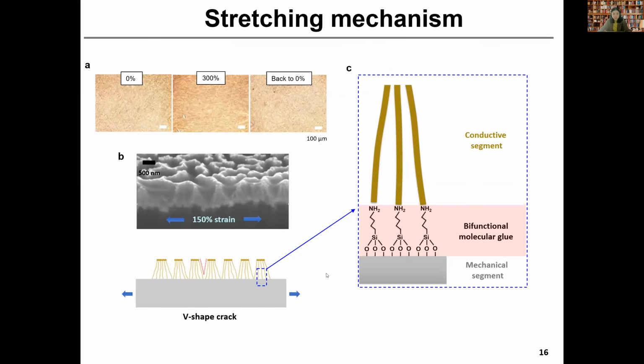So why can this film be stretched so much? This slide gives us an explanation. Because of the unique Janus structure, the top layer of the film is more rigid than the underlying layer. So when the stretch begins, the nanoparticles start to separate. When we continue to stretch, the nanowires begin to separate, but the bottom layer of the nanowires remains connected. This is also due to the glue function of the molecular glue, which provides good adhesion between the nanowires and the soft substrate.